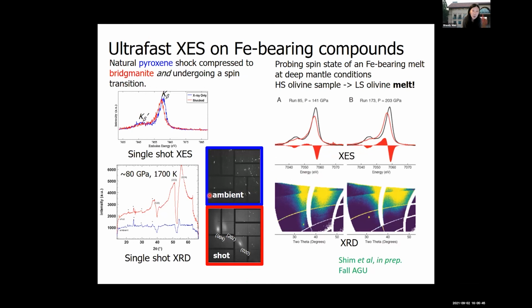he'll also be presenting at fall AGU. But the point here is that in single shot, we can collect X-ray emission spectra and X-ray diffraction patterns on the same sample. And this enables you to see the spin transition and structural transitions in the same shot. And because we're using laser shock compression and these ultra fast timescales, we've actually been able to look at melt. So here are some X-ray emission spectra from olivine melt that's been shock compressed to 141 GPa and 203 GPa.